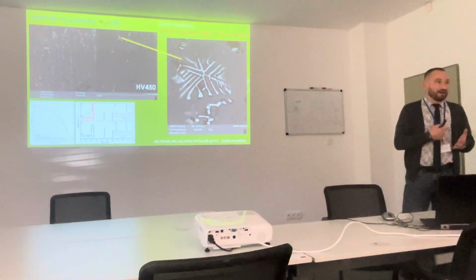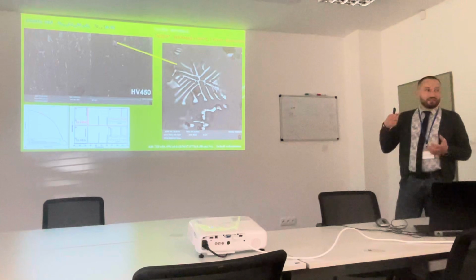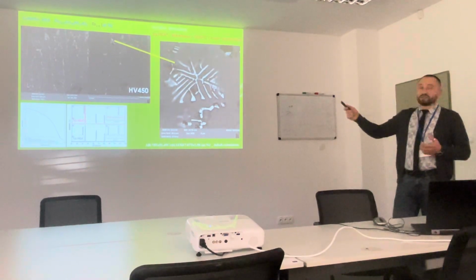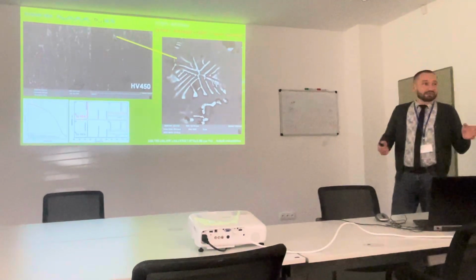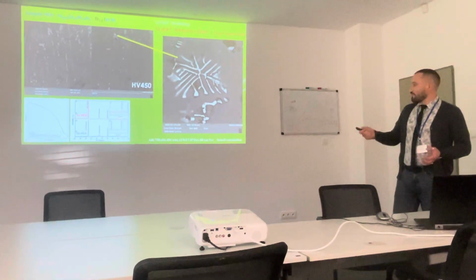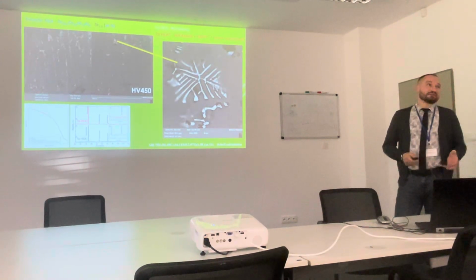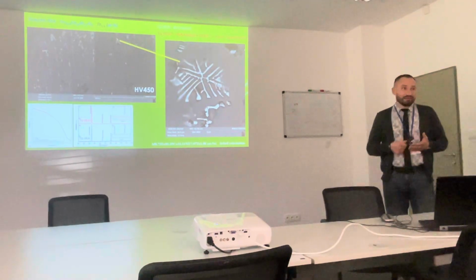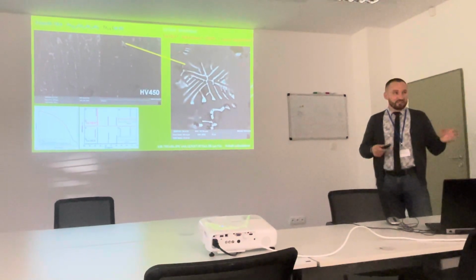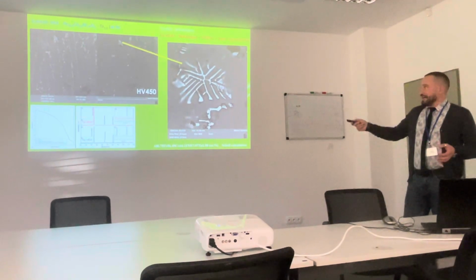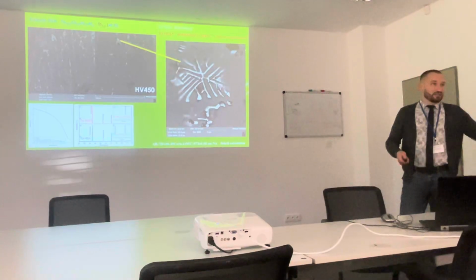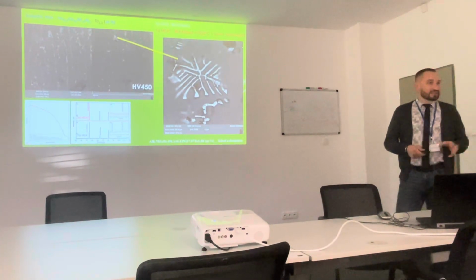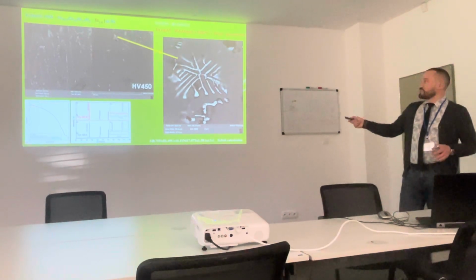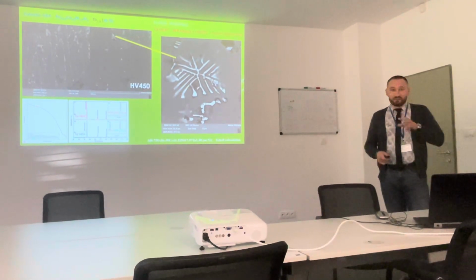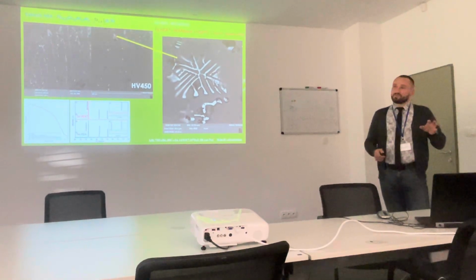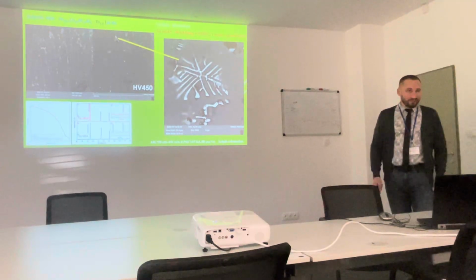And the next one is a high hardness high entropy alloy. In this case, we introduce into the alloy system aluminum and a little bit of refractory element, tantalum. And as printed material, we obtain the biggest hardness of 450 HV. It's really high, comparable with armor steels. And it was surprising that after printing, actually multi-layer welding, there weren't any hot cracks or cold cracks. However, the plasticity of such composition after printing was extremely low, near 2 or 3%. It's an absence of plasticity.